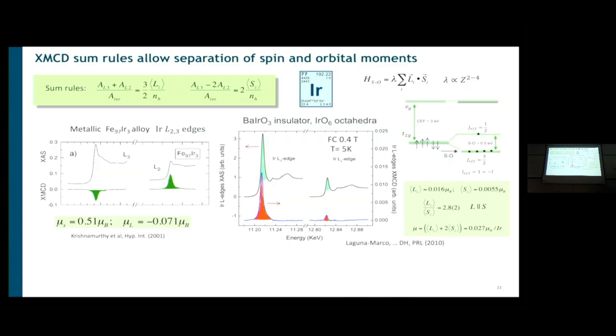If you have, for example, an iridate that has very strong spin-orbit coupling, but now it's not a dopant, but it's actually a band material where the 5D band is split by spin-orbit coupling, and the orbital moment is not quenched. You see that the XMCD at the L3 and the L2 edges not only don't have opposite signs, but one is very large, the other is very small. And that already tells you that there is a very large orbital moment in this iridium 5D wave function.